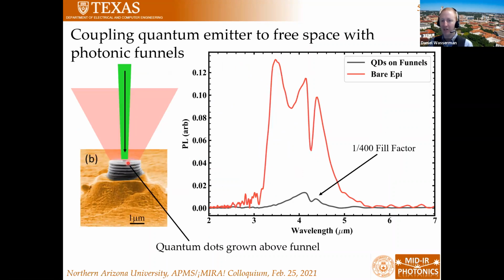And then most recently, we integrated some quantum dots into the top layer of this funnel. And we showed, in fact, that we can get an appreciable photoluminescence signal. This might not look that impressive, but you have to remember that we've basically etched away all of our dot material. So this is what you get just with the bare epi material. When you etch away everything except for that very tip of the funnel, you're still getting only about a factor of 10 or less decrease in your emission efficiency, but you've essentially killed the fill factor of your emitter by a factor of 400. So we're looking at ways that we can integrate quantum emitters into these hyperbolic photonic funnels in order to connect, ideally, single photon emitters at the nanoscale to the far field using these types of hyperbolic structures.